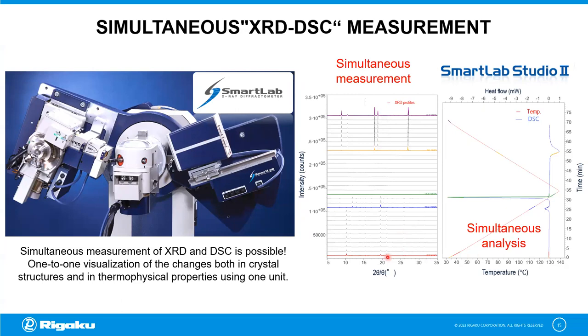So here's an example. On the right, we have the DSC pattern. We're changing the temperature here. We then see the change in heat flow as blue, green, red lines here. And then the change in diffraction pattern is shown here. So we have a phase here. We reach the melting point. This large endotherm is the melting point.